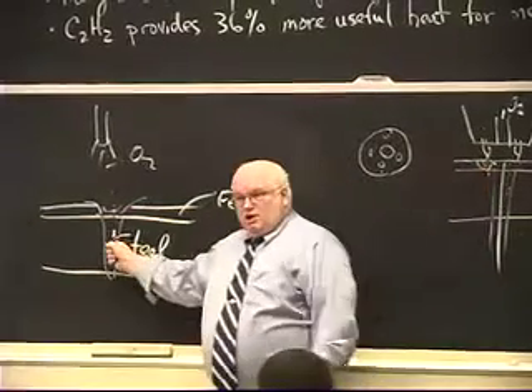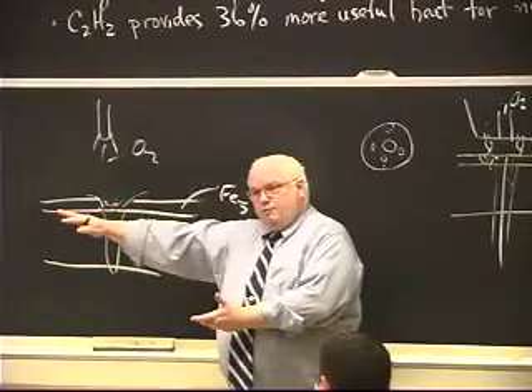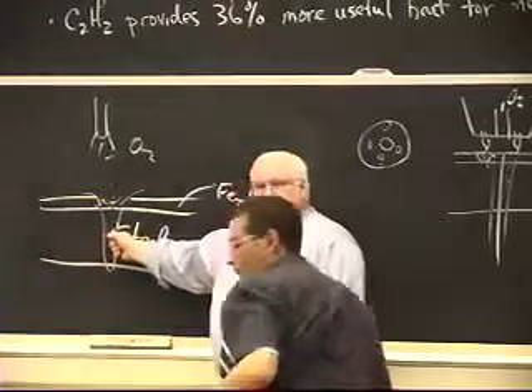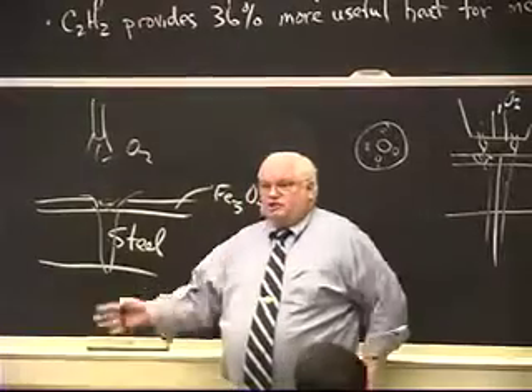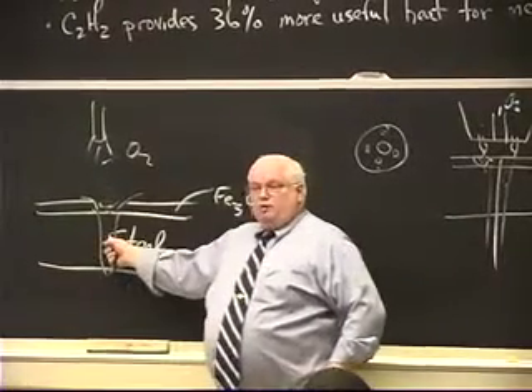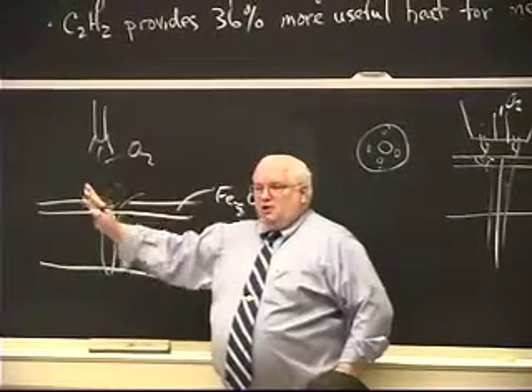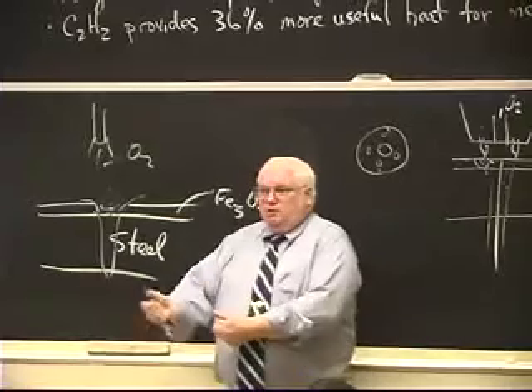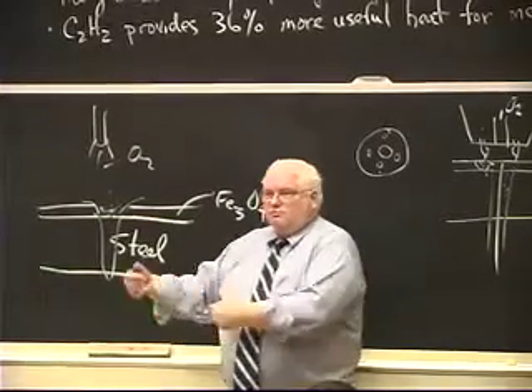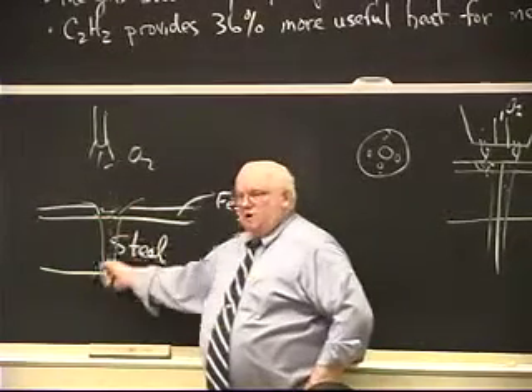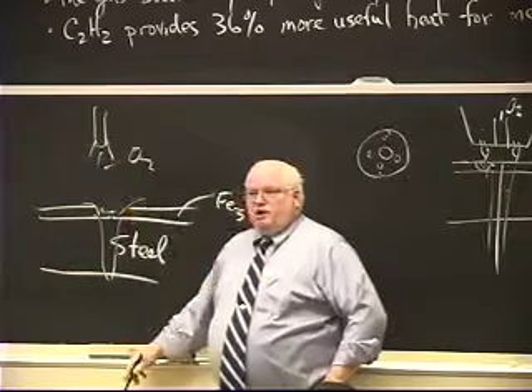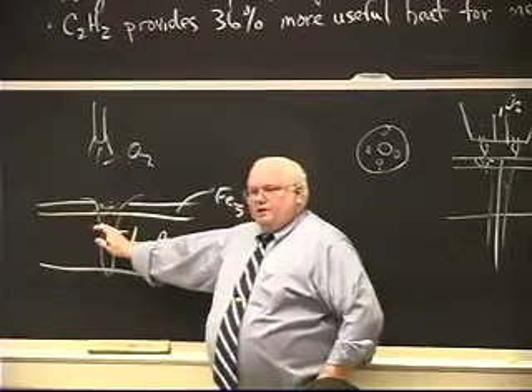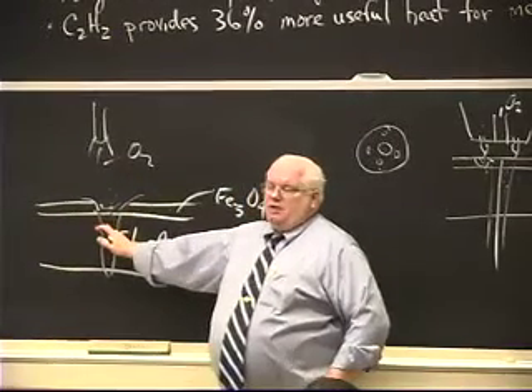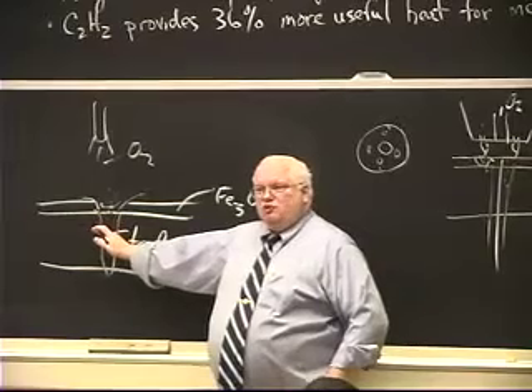In the steel mill, they might be cutting these slabs that are coming off the casting furnace, and they're typically 12 inches thick. They don't need to preheat them with a little flame because they're solidified. They just solidified. They're already hot. And you hit them with a pure oxygen lance, cut right through them. So the guy's just got a great big pure oxygen torch so he can go around, you know, and wherever it is, he just slices right through it, and it can cut through this at probably several feet per minute through 12 inches of steel.